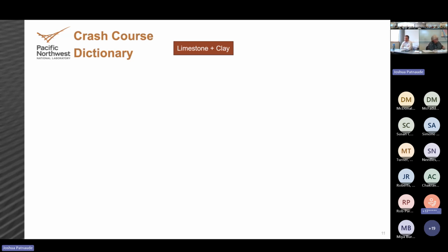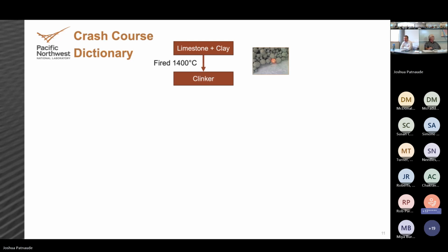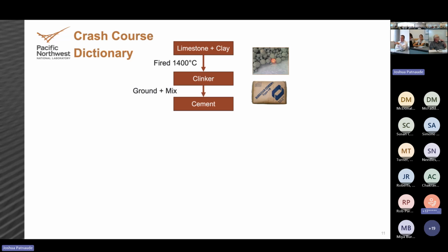So what we start out with to get to a cement product is limestone and clay. You mix them together, put them in a kiln, and you heat it up to about 1400 degrees Celsius. What comes out of that kiln are these little nodules, and those nodules are called clinker. This is a material that contains that tricalcium silicate, that dicalcium silicate, those reactive compounds that will end up making those hydration products. So the nodules that come out are clinker. This is the main reactive component of cement.